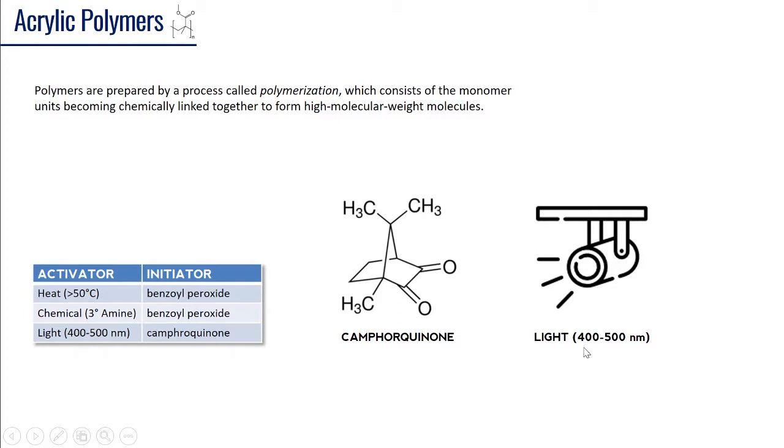Our composite, remember, we shine a light generally in that 400 to 500 nanometer wavelength range to start this polymerization reaction of composite.